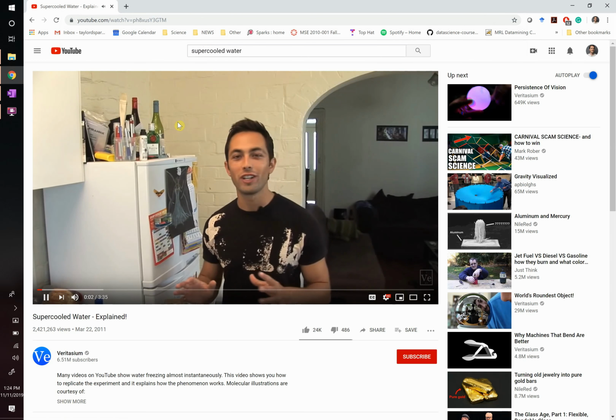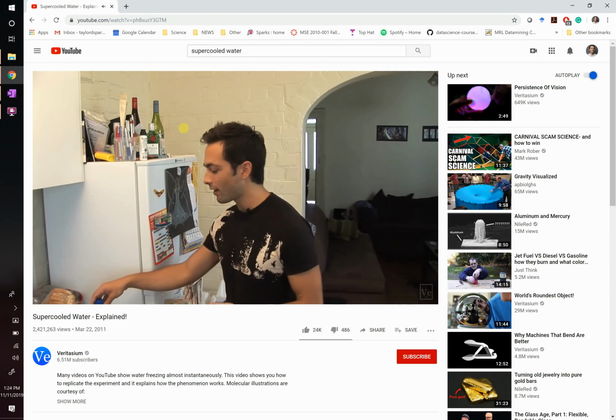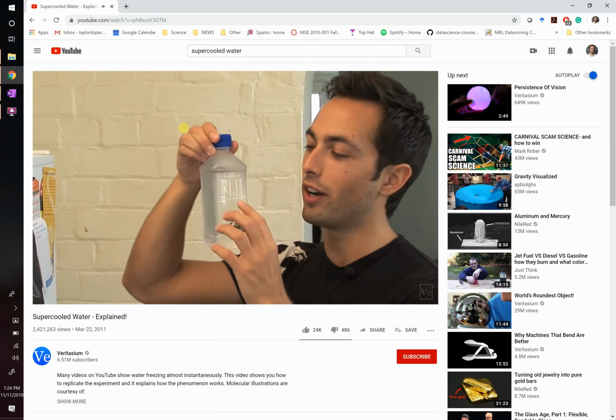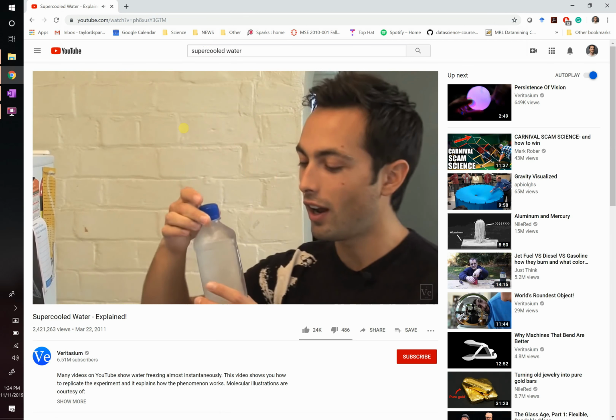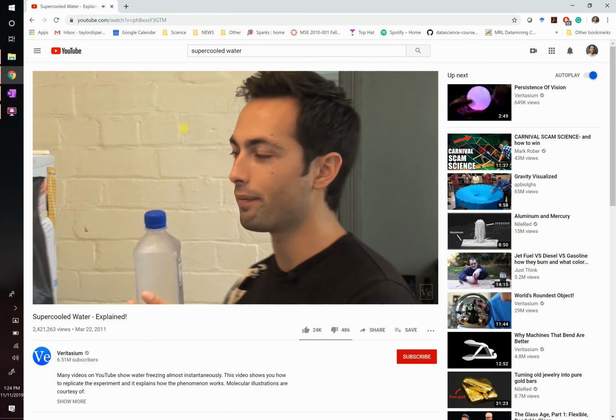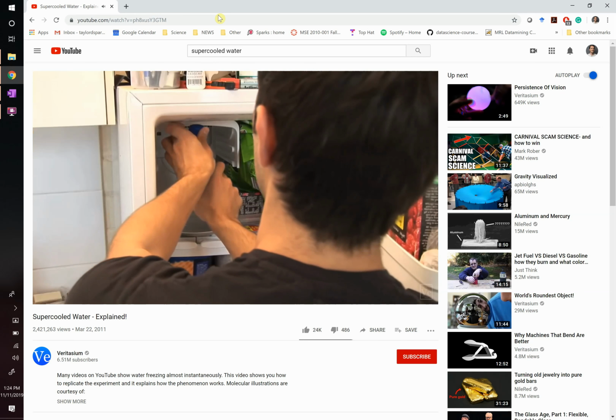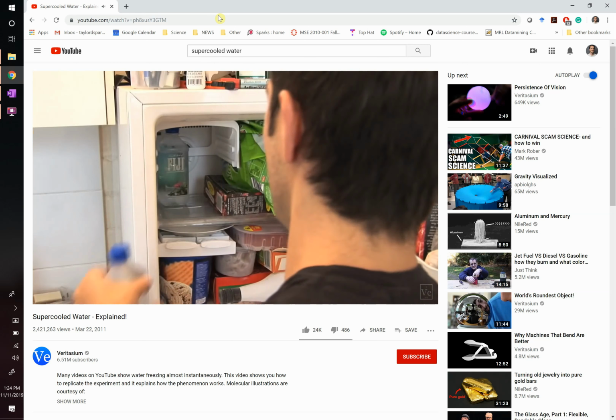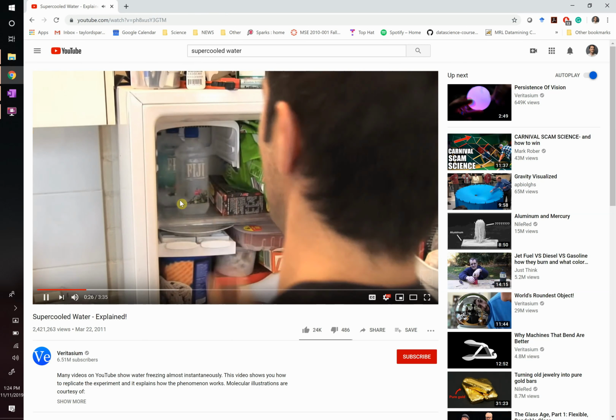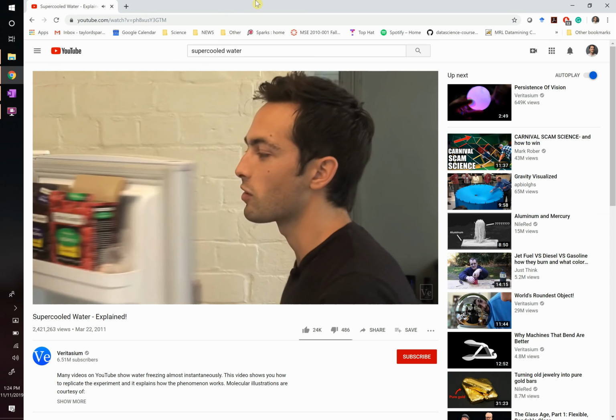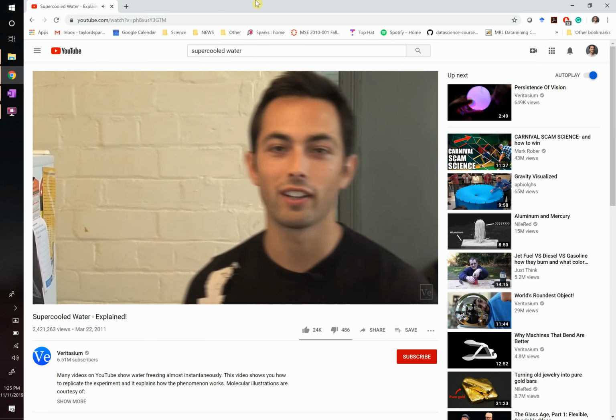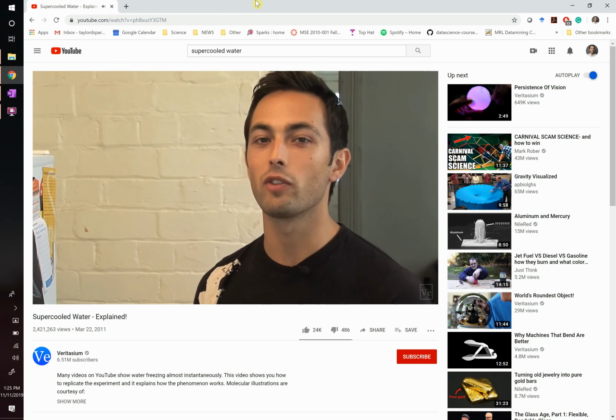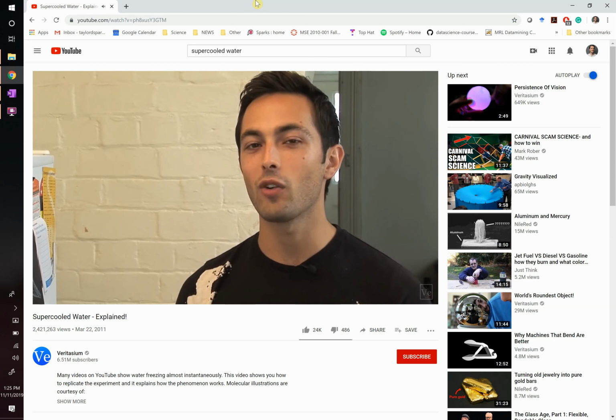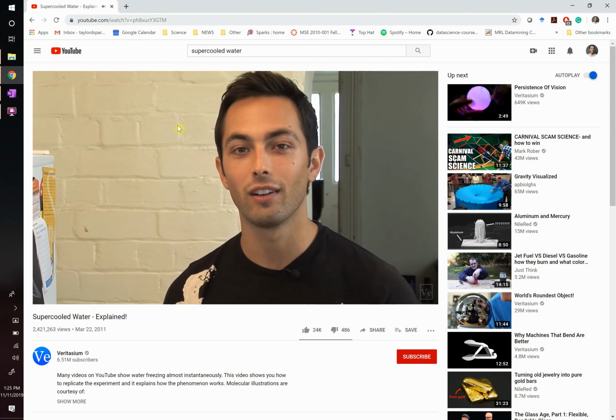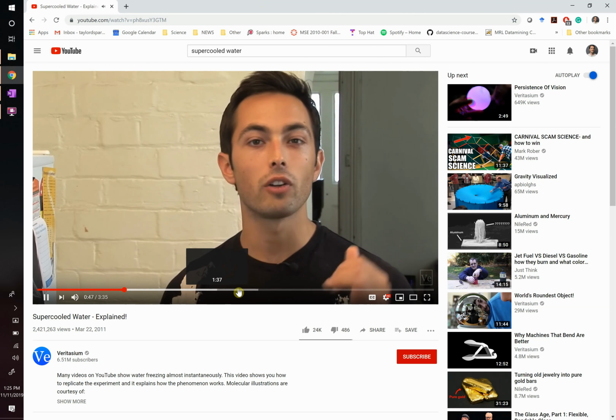Okay, so it works best if you use Fiji water, for reasons that depend on the purity of the water. If you use tap water, it's full of ions. What are ions going to serve as? Heterogeneous nucleation sites. So that's going to cause it to freeze really easily. So this guy took a Fiji water bottle, which is more pure. He put it in the freezer. If you let it sit too long, it will eventually freeze, depending on how cold your freezer is. He's putting it directly on that metal plate, which usually won't work, because the metal plate's typically a lot colder than the air, and so that's going to serve as a site that is much colder than the air around it. If you put it in a thermos, it tends to work better. Put this thing inside of a thermos, and then slowly, from all directions, this cold temperature comes in. If you let that sit for apparently longer than 3 hours, like I tried this morning, and come back to it,